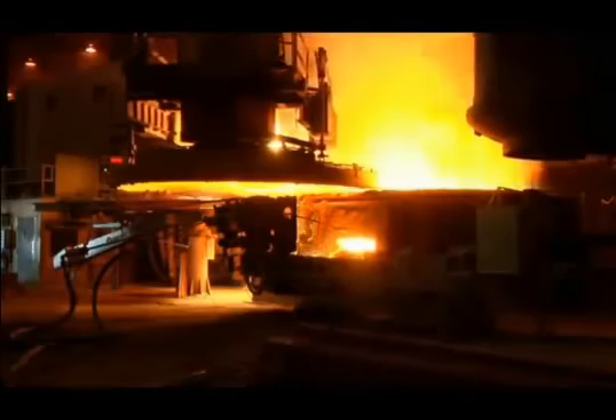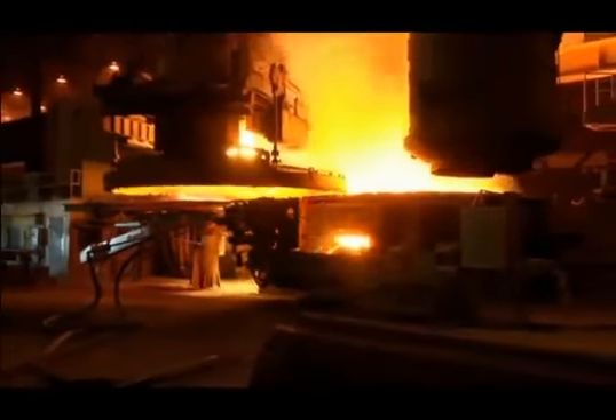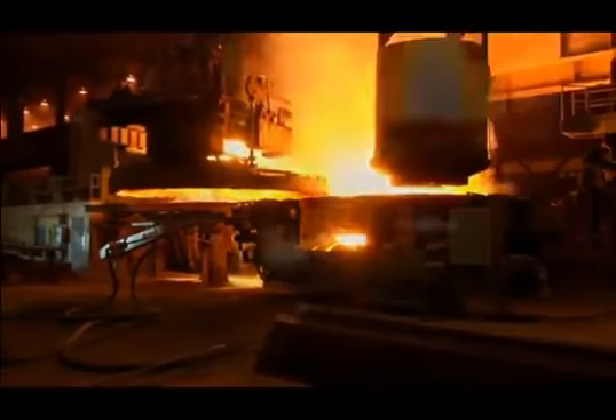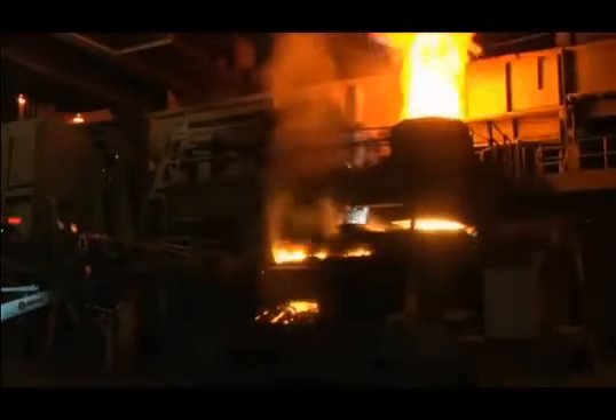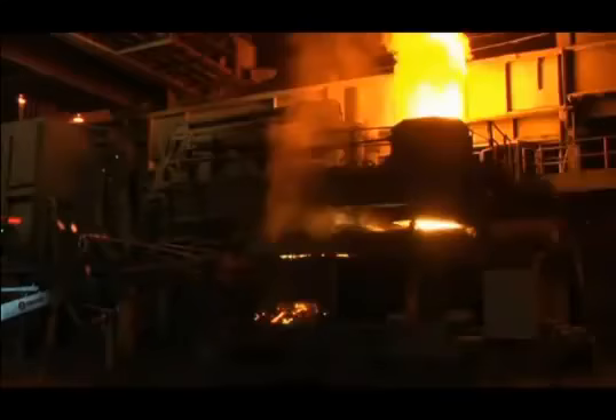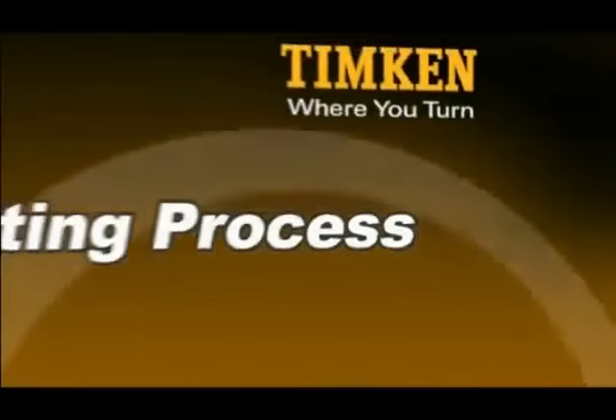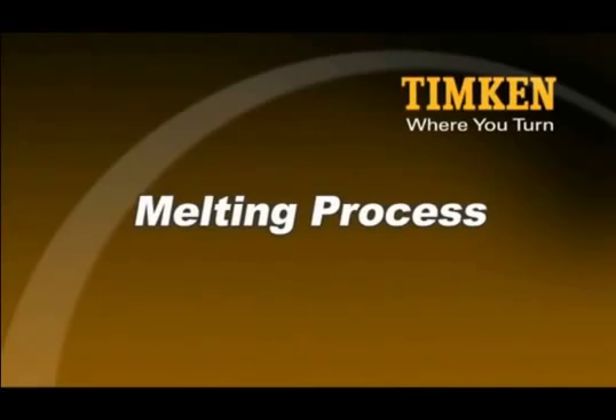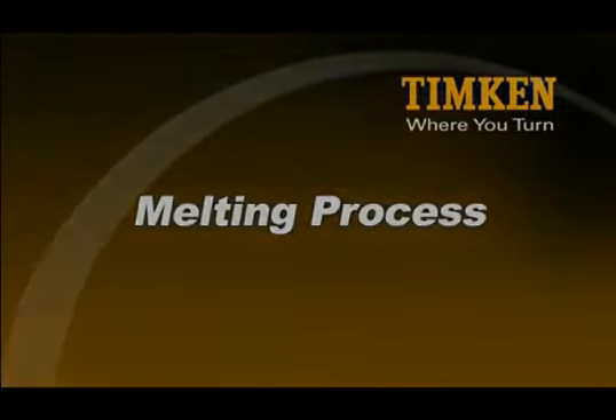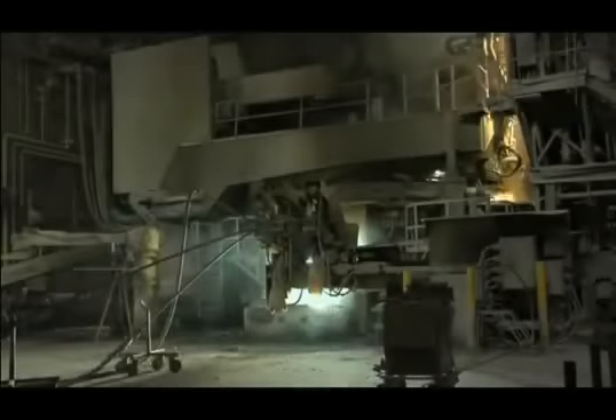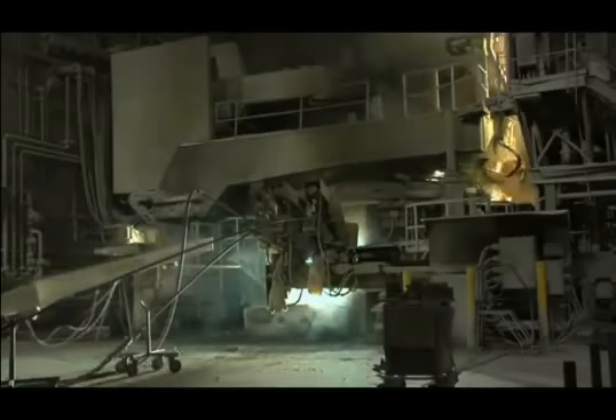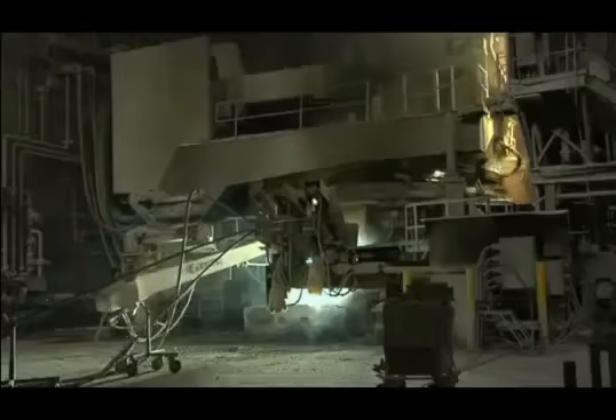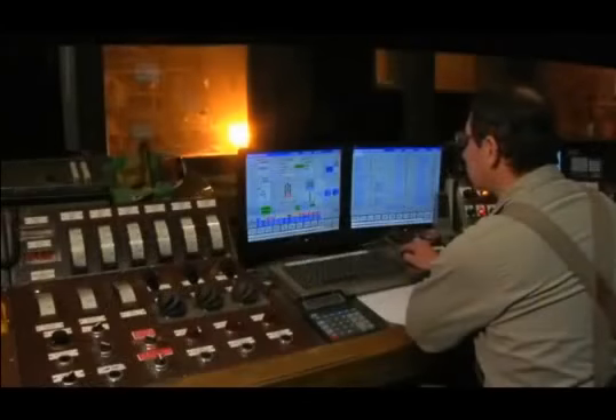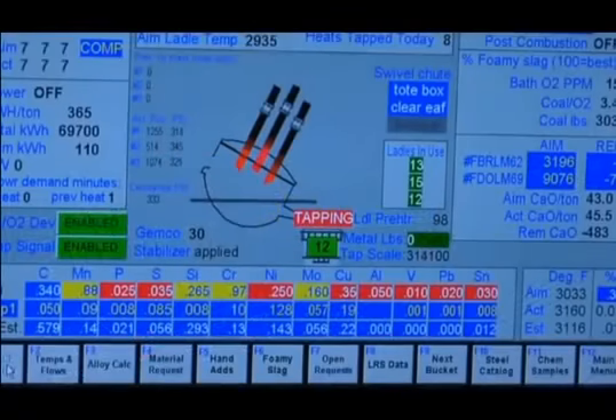At the steel mill, scrap buckets are filled with a scrap blend. Lime is added to produce slag, and then the scrap is charged into one of our 3 electric arc furnaces. Electric arcs jumping across 3 carbon electrodes create controlled lightning in the steelmaking furnace, reaching temperatures of 3,000 degrees. In less than 2 hours, the highly efficient electric arc furnace has reduced the scrap to molten steel.